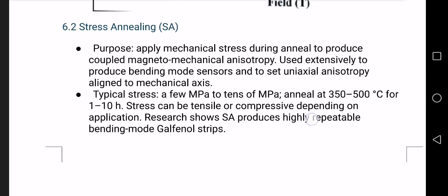Now next we have stress annealing. Purpose is to couple mechanical and magnetic anisotropy. Typical conditions are stress of a few MPa to tens of MPa, temperature 350 to 500 degrees Celsius, time 1 to 10 hours. Used widely for bending mode sensors and highly repeatable devices.